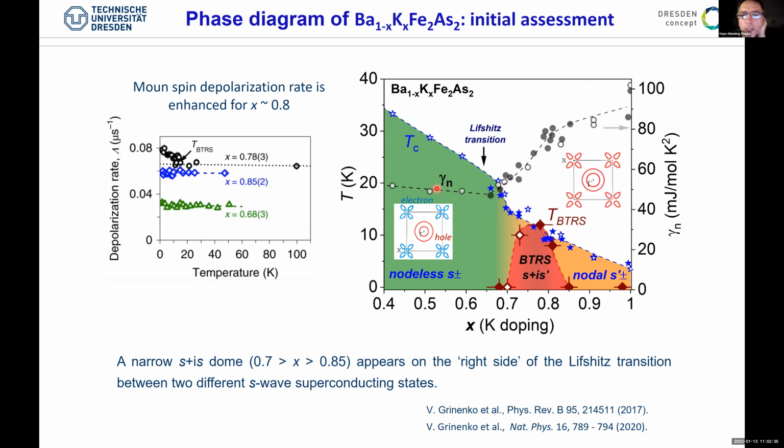First off, well, I don't have a strong opinion on that. Basically, some colleagues have made some theoretical calculation of the Sommerfeld coefficient, but it's in a planar situation, in a planar model. Then you see, for example, a peak. You expect really a peak of the Sommerfeld coefficient at a Lifshitz transition. First of all, in the experiment that is broadened, but secondly, since there's a warping along the z-axis, probably even if you have a nice high quality sample, it's simply washed out. It gets broadened.